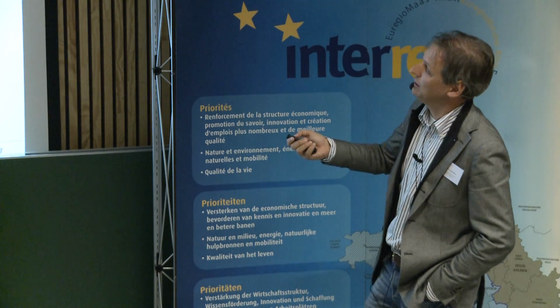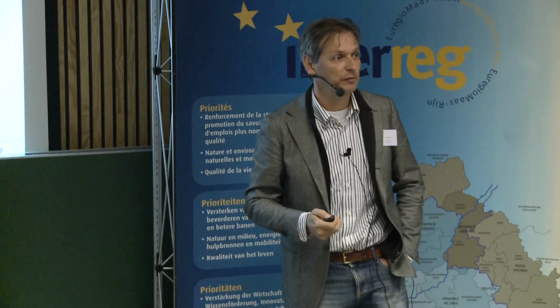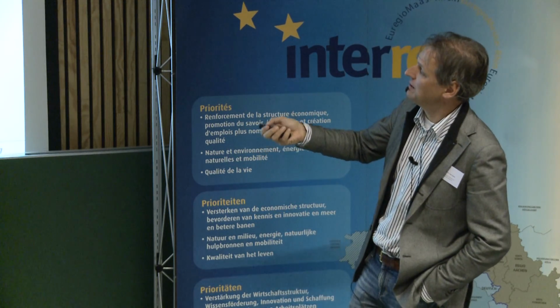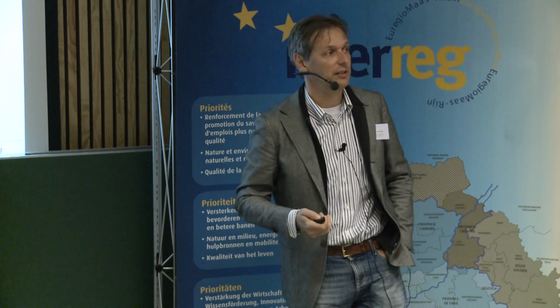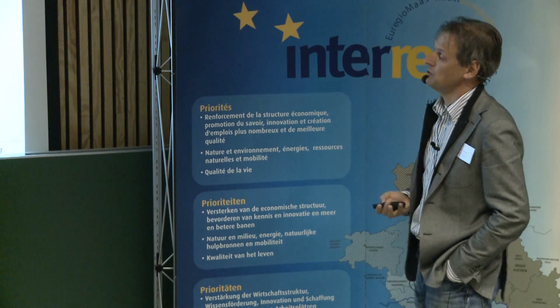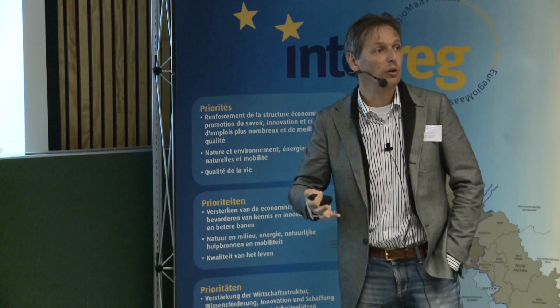Later on, together with the group of Peter Bobbert in Eindhoven, we made a model where the mobility depends on the density and the temperature and also the electric field. And with this, you can nicely describe the whole transport in such an LED, or in a conjugated polymer. And it's not only valid for MEH-PPV, but basically for all polymers.